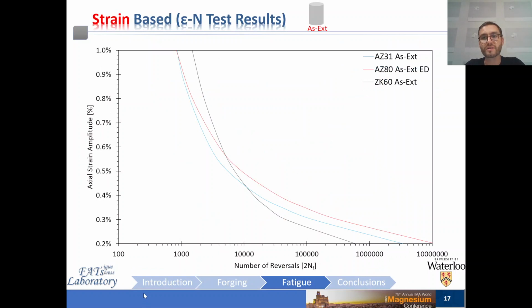Now to look at all these effects and how they relate to fatigue, here you can see a typical strain life curve that you're familiar with for all three of the alloys in the as extruded condition. So that's AZ31, AZ80, and ZK60. AZ31 in blue has the lowest strength but moderate ductility, manifesting itself here as the lowest life in the low cycle regime at high strain amplitudes. AZ80 shown in red has the highest ductility amongst the three alloys, illustrating the highest life in the high cycle regime at low strain amplitudes. And ZK60 shown in black has superior strength in the as extruded state relative to the other two alloys at the expense of limited ductility.